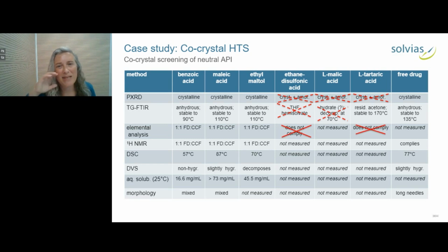Then looking at elemental analysis, we saw that while we had nice stoichiometric ratios with benzoic and maleic acid and ethyl maltol, 2 of the samples did not comply. And at this point, we decided not to consider the 3 formers on the right, but just focus on the first 3.